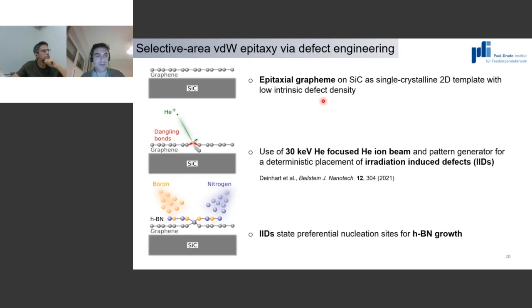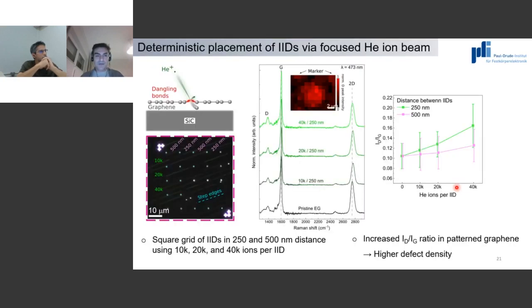So we got this graphene substrate. Here I'm not representing the buffer layer, only the graphene. We use a helium-ion microscope from colleagues from the Festkörperelektronik Institute to write a pattern of what we call irradiation-induced defects in graphene with a low energy, helium-focused ion beam. And finally, we take the sample, put it in the MBE, and grow HBN. If we are right that even point defects would lead to nucleation, we should be able to start growing where we have these defects.